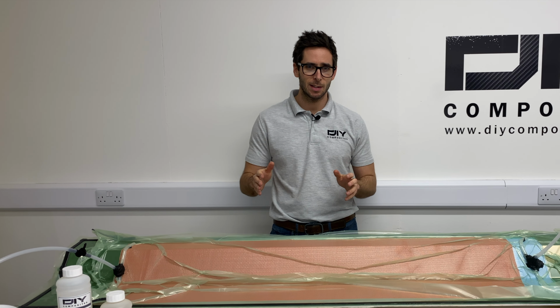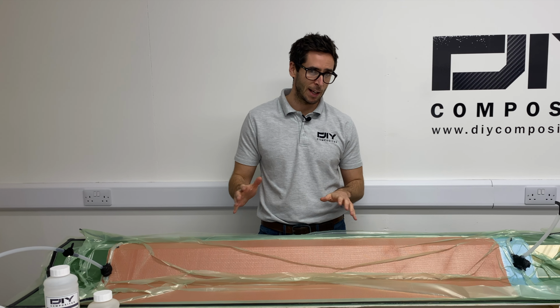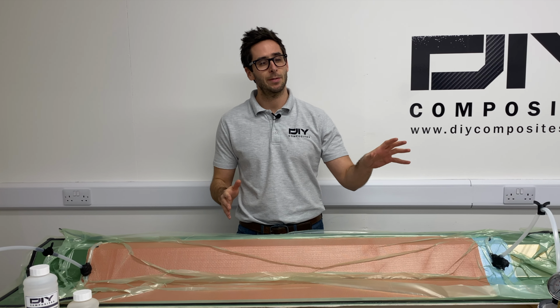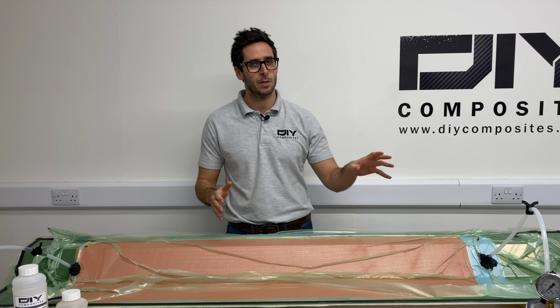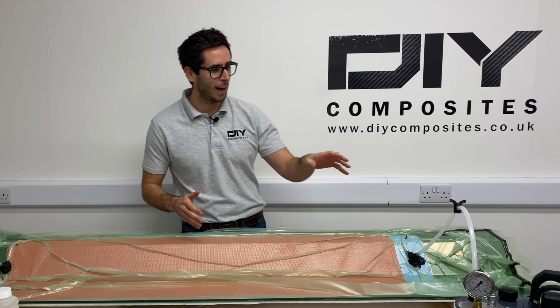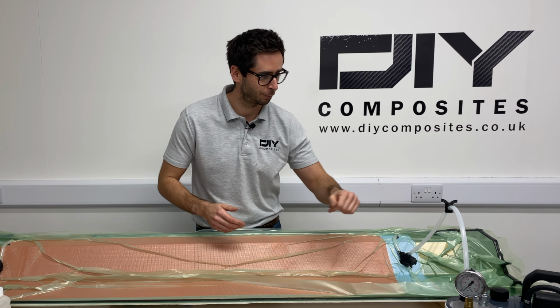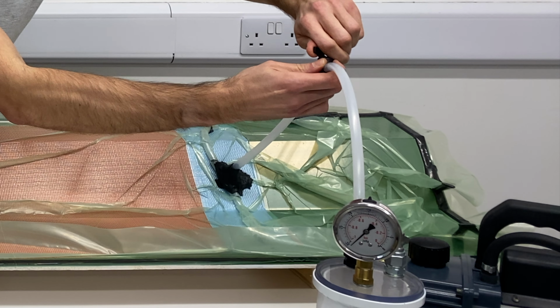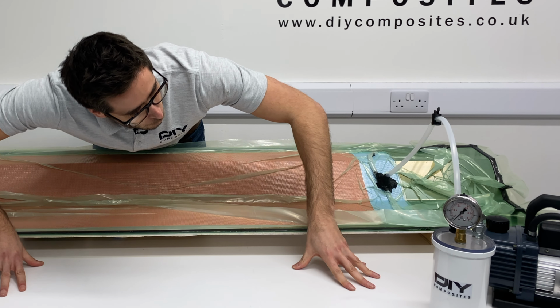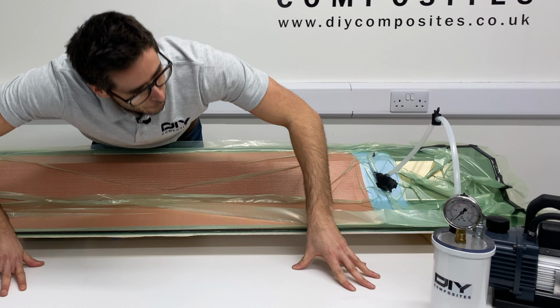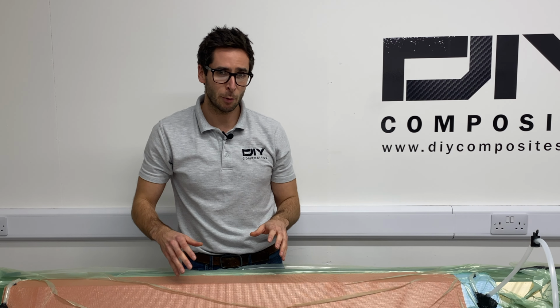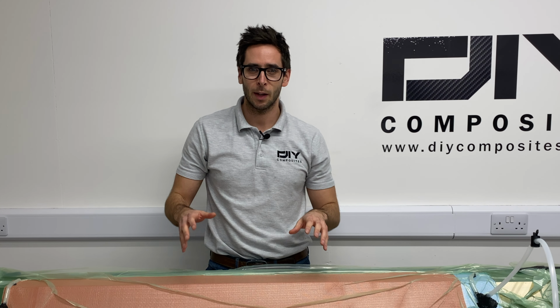We've now completed our 30-minute purge of the bag to get rid of any air. We then disconnected from the vacuum source and have done a 30-minute drop test to make sure we have a good bag. The next step is to open the valve here and see if we get any movement on the needle. Nothing changed, so we know we have a really good vacuum bag and it's time to mix our resin.